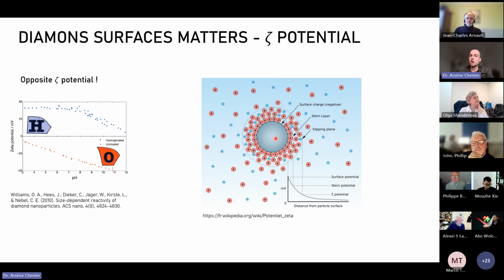And this surface charge will attract ions from your liquid that will create the Stern layer and the diffuse double layer, Helmholtz layer, etc. And those ions will be carried out with the particle. And what we call the zeta potential is the electrical potential happening at the slipping plane here in the electrolyte. And this electrical potential will vary depending on the ions that are around the nanoparticle. So simply put, the zeta potential is a way to measure the surface charge of the nanodiamond.